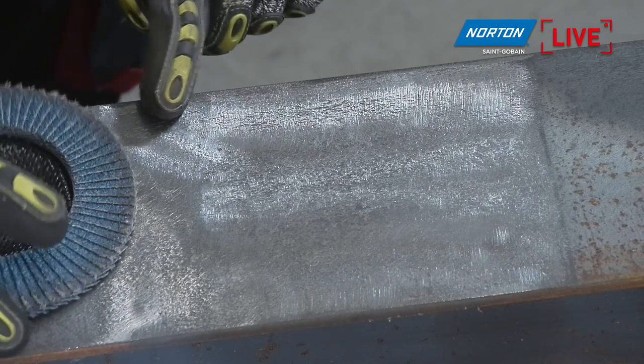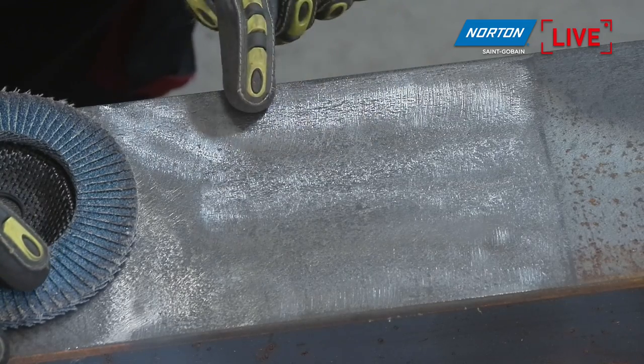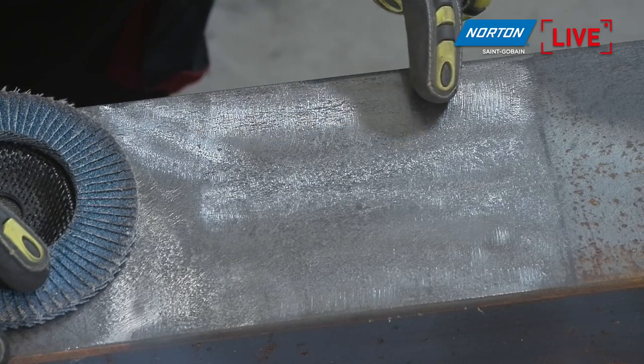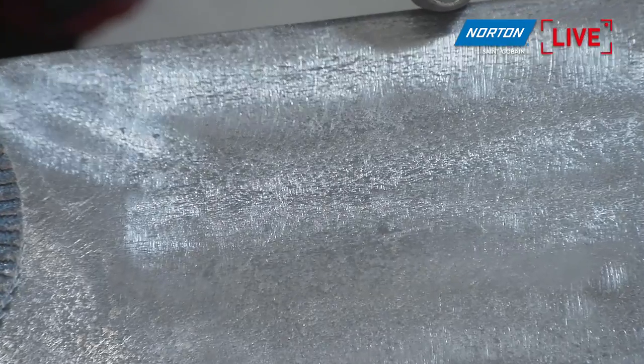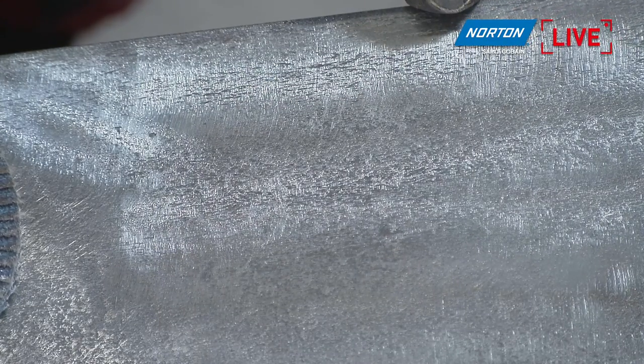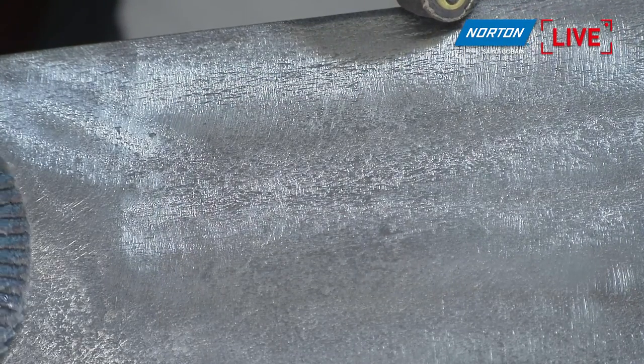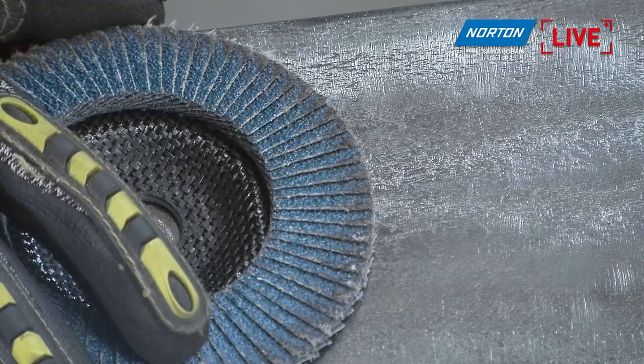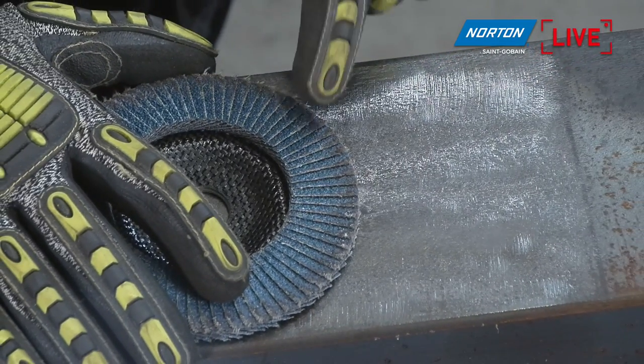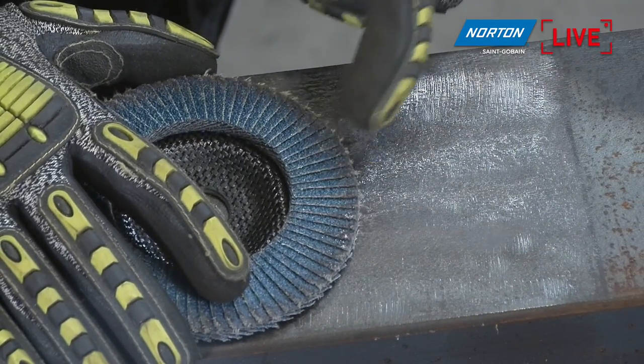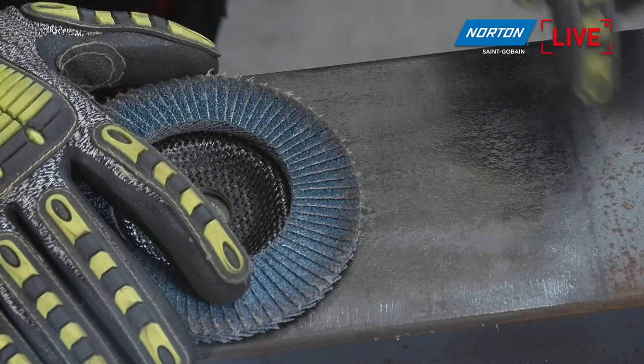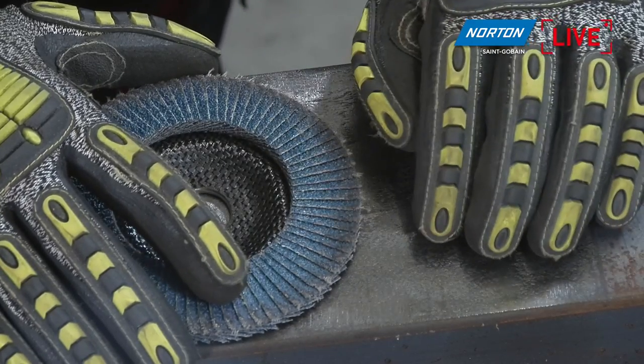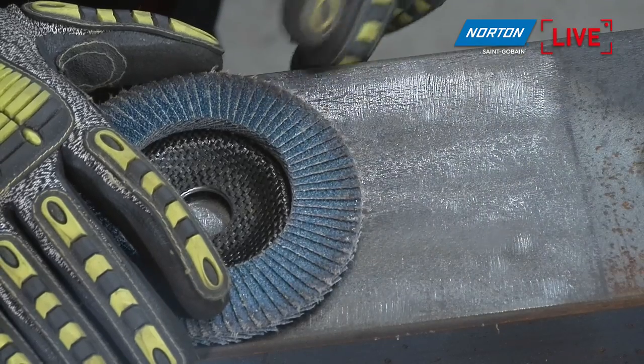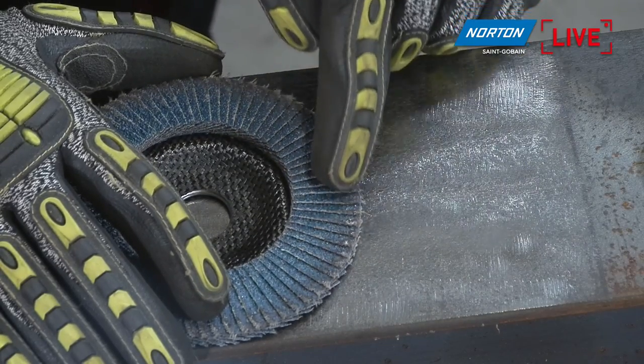But I do notice that we have put some scratches in here. I think you can see the radial scratches on here. Yeah, you certainly can when you zoom in there. Thank you very much, Martin. So we have put a bit of damage into the material, but also look at the flap disc itself. What we can see, it's breaking down nicely. That's what we want. We want the flap disc to break down to release the abrasive on the flap under the top surface. But what I can see here is a lot of black on the edge.